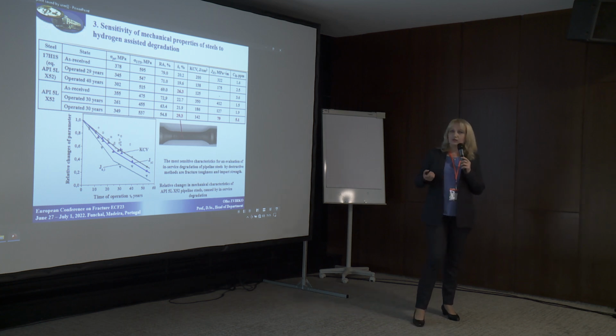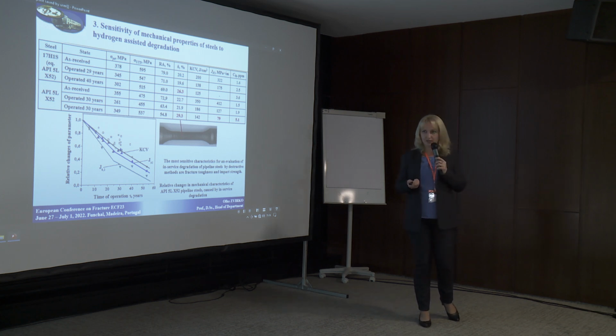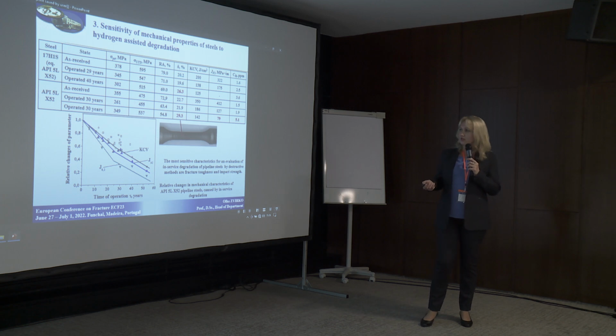However, based on many researches, strength and hardness and also elongation, as I showed, aren't sensitive enough to in-service degradation of pipeline steels. So to correctly assess their degradation degree, it's important to choose informative indicators which are sensitive to degradation. And the most sensitive are fracture toughness and impact strength.